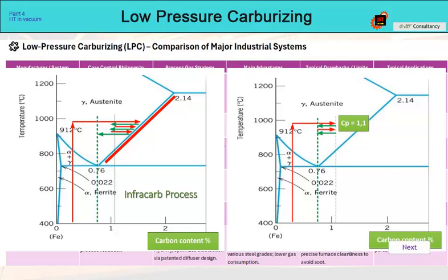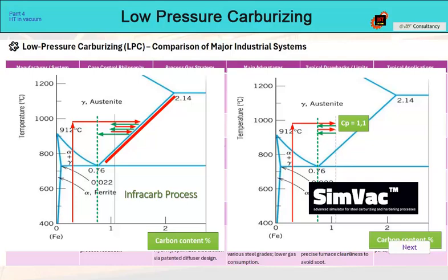On the other hand, there is SimVac, which uses a thermodynamic model. It tries to simulate a situation with a defined saturation potential CP, as is the case with multipurpose furnaces. Although it works quite well in practice, the disadvantage of this system is that we need to know the surface area of the batch. This will be a problem in most heat treaters, and if we get it wrong, there may be too little or too much acetylene. However, because this calculation method does not use the maximum carbon gradient, the process will be slower than infracarb.